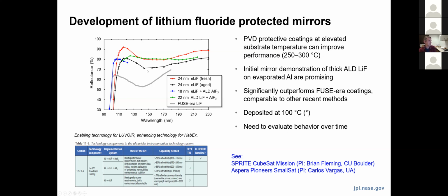And so some of the things that we've been looking at with ALD is, one, maybe taking some of this ELIF material and putting an extremely thin encapsulation layer on it. That's an example shown in this blue curve here that has been done in collaboration with the University of Colorado. Here, using a very thin encapsulation layer of aluminum fluoride. So the idea is that the encapsulation layer is thin enough that it doesn't create enough absorption loss at these short wavelengths to degrade the performance of the mirror, but thick enough that it can seal in the chemical stability in the lithium fluoride.